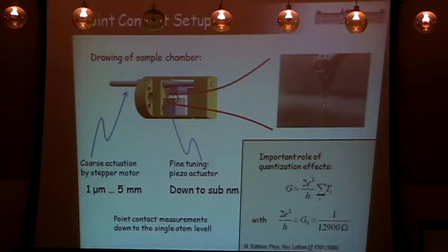But this is not necessarily the case. It can happen that we have 100 tunneling channels, each of them contributing 0.01, which will lead us to the same conductance value. For silver itself, this data does not reveal the distribution of these T_i values, but other experiments and molecular dynamics calculations show that for silver, one has one single conducting channel.